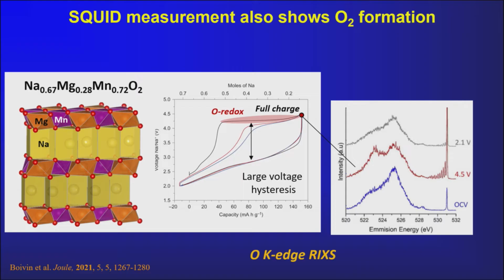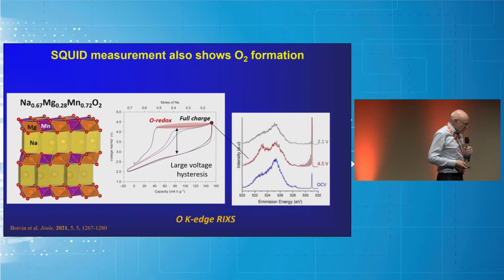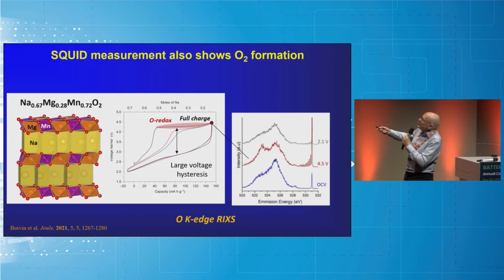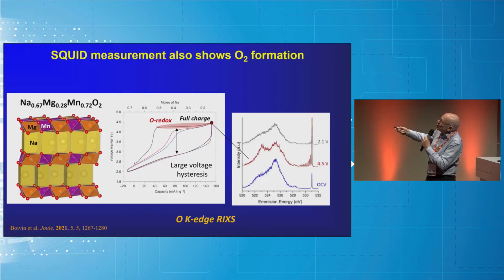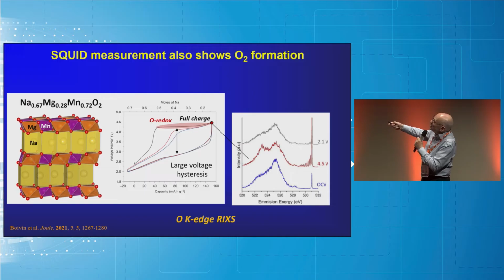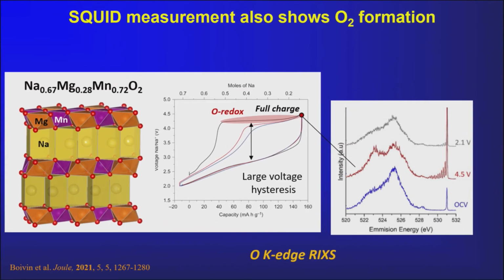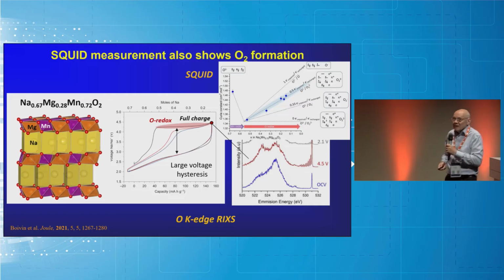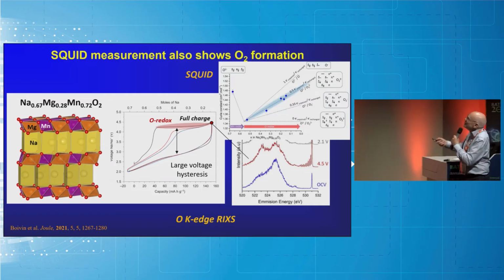But the nice thing about this material is it is very simple in terms of spins. You can't quite make the perfect 1/3, 2/3 stoichiometry, which would mean all the manganese was already 4+. So you have to oxidize when you charge the material and take some sodium out. You have to oxidize a little bit of the manganese till it's all 4+. But from then on, you've just got manganese 4+, d3, and anything else that happens is on the oxygen. So it's great for doing magnetic measurements. And that's what you see here.